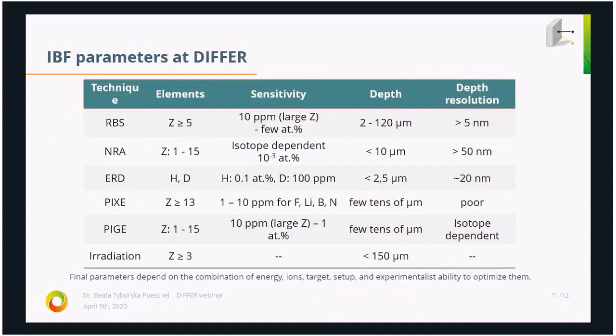Okay, so here are the IBA parameters which we have. I think we have them on our website as well. So as I said, the plus of RBS is a very high depth resolution. NRA, PIXE, and ERD can detect isotopes, especially PIXE can go to very, very low ppm values. And then the depths which we can analyze, this of course all depends on the type of ions you use and on the type of target you have. But with RBS, we can go up to maximum 120 micrometers. And for irradiation, we can go even 150 micrometers if we irradiate light targets with protons.